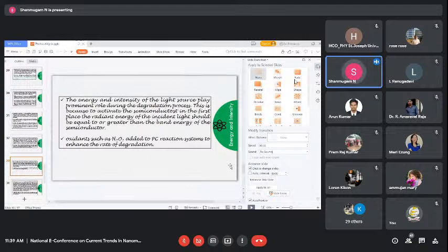Usually for practical applications we use sunlight. Sunlight carries only 5% UV radiation, so if you perform the experiment with the help of UV light, the activity can be enhanced. But for practical purposes, we are motivated to utilize sunlight, even though it has only 5% UV light. For that, the catalyst should be enhanced by way of doping or composite formation.